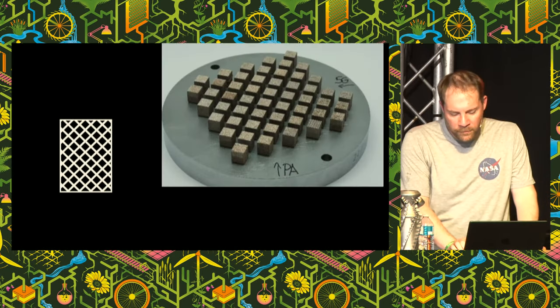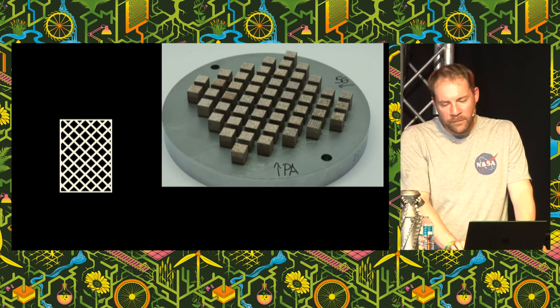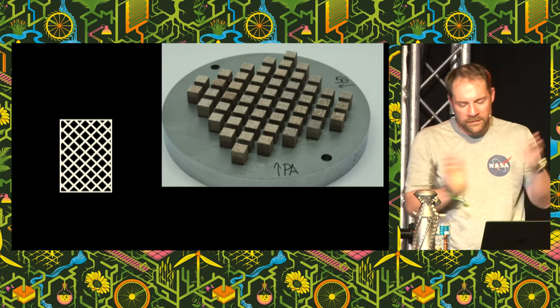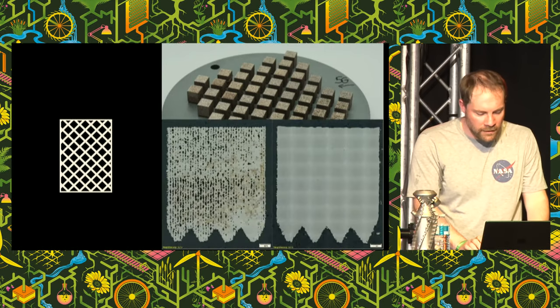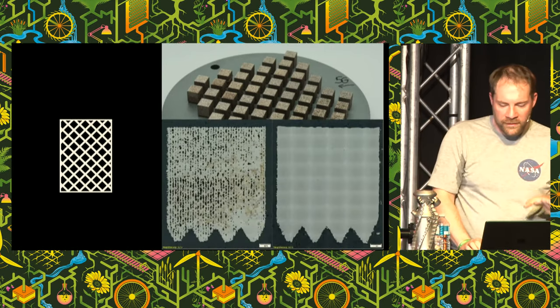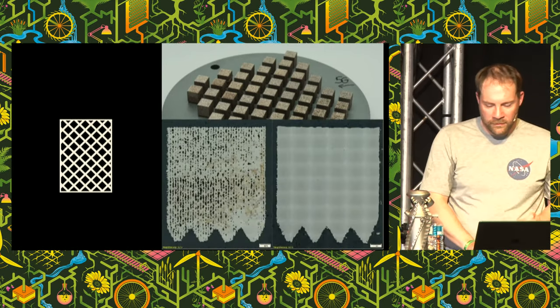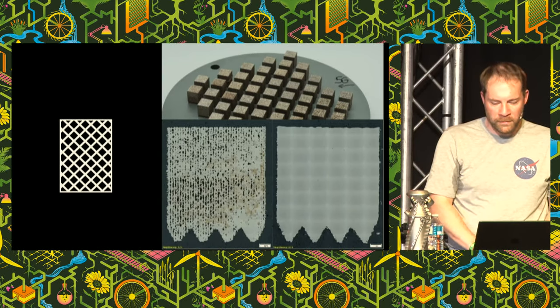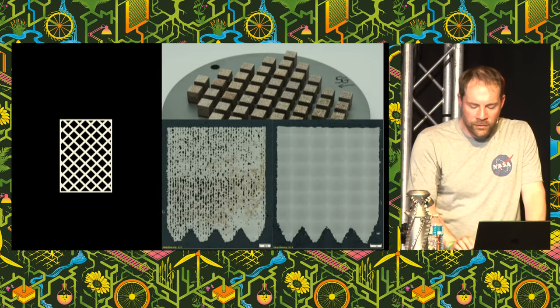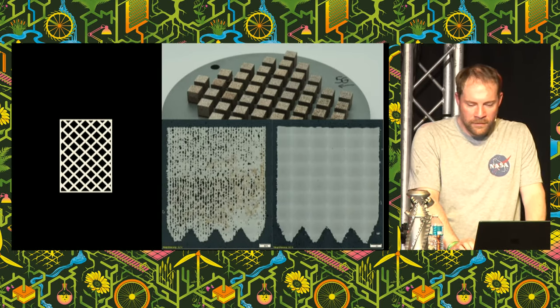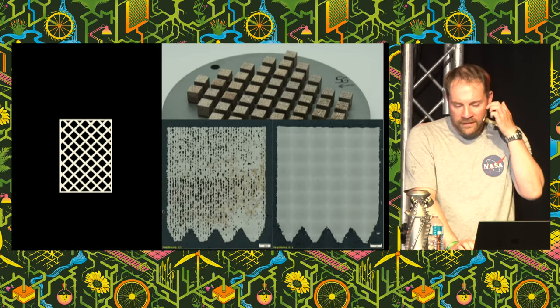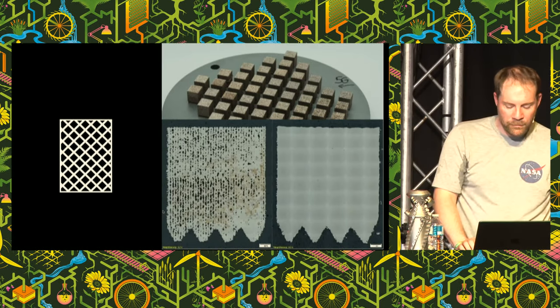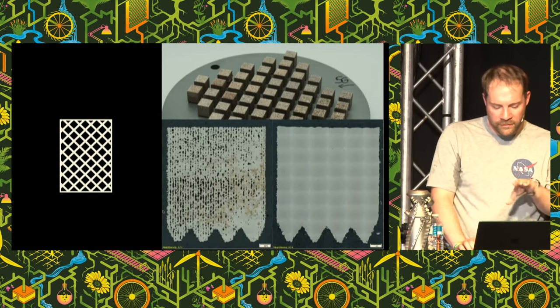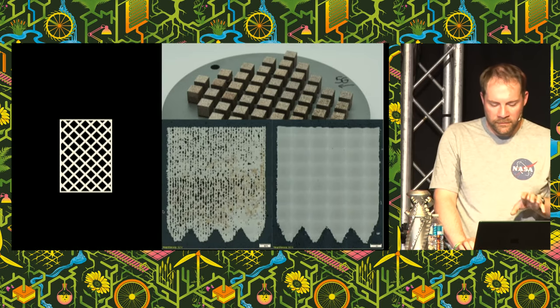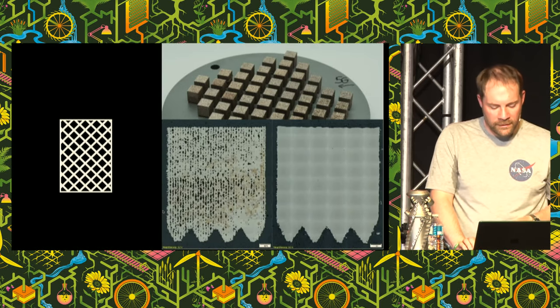So we did a bunch of samples with different laser parameters, different laser powers, different distances, different contour speeds, polished and analyzed them, and you can see there's one that's very porous and would not be strong enough. Here's one that's completely solid. And we tried a few, selected a laser parameter that looked promising, and then printed some test pieces that tried out this kind of transpiration trick and a couple of other tricks to try and let some of the propellant leach through.